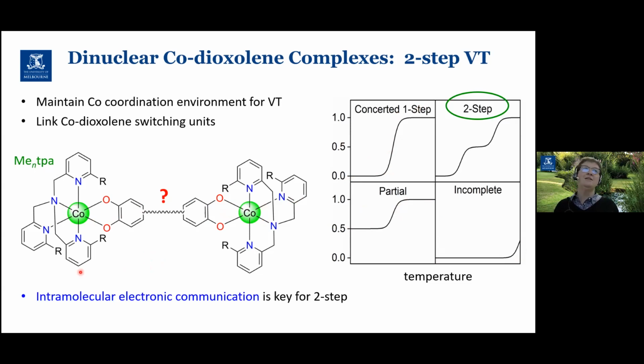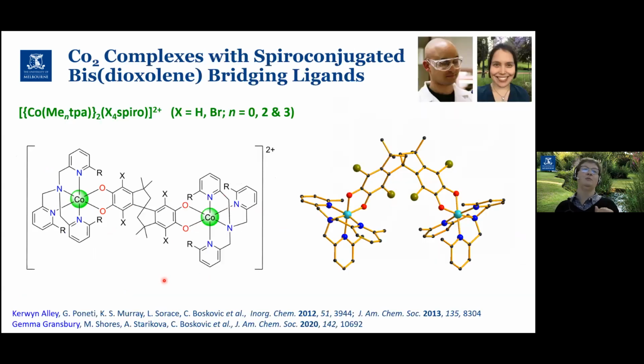So I'll tell you now that the answer really is to do with the intramolecular electronic communication between the two cobalt-dioxolene halves of the dinuclear complex. So if you think about it, it does make sense. If there's no communication, if these two halves of the dimer can't feel each other, then they're both going to go at the same temperature. In that case, what you'll see is a concerted one-step transition. On the other hand, if you have full conjugation or delocalization, then essentially you're only going to get something like a partial or incomplete transition. So for the two-step transition, you want some electronic communication, but not too much. And that's the key, as I'll hopefully show you as we go through.